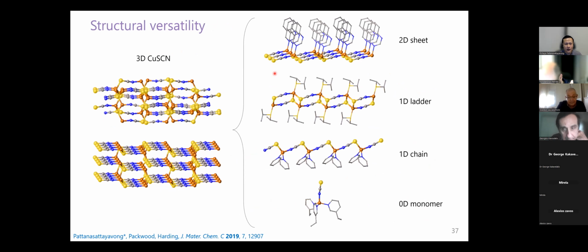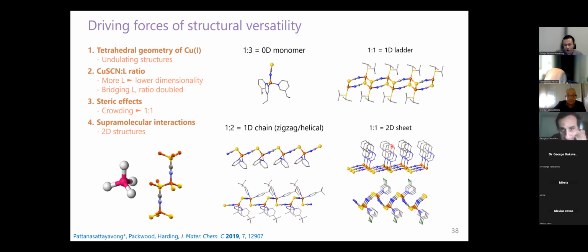Right? And then when there's an extra ligand, it would compete with the thiocyanate ligands basically, and then it would link or cap on one of the sides of the copper. In this case, it would form quite a flat 2-dimensional sheet. And other structures are possible depending on the ligands that we choose.